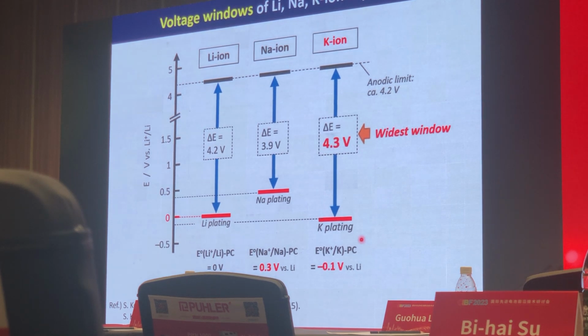electrochemistry medium is based on propylene carbonate or EC or DEC like carbonate ester solutions. They are not aqueous solutions. So potassium operating potential is lower than lithium in propylene carbonate electrolyte solution. Then a wider potential window than lithium and sodium means that it is highly advantageous for higher voltage operation, which will lead to higher energy density by using the same capacity electrode materials for positive and negative electrodes in lithium and potassium cells.